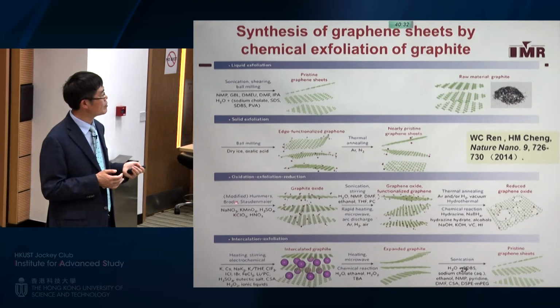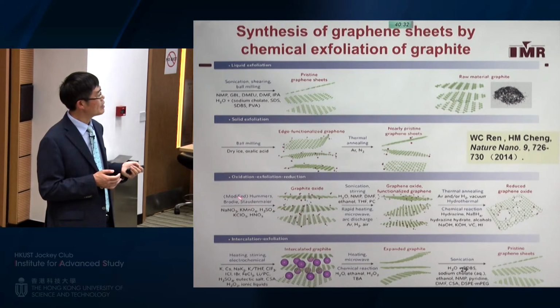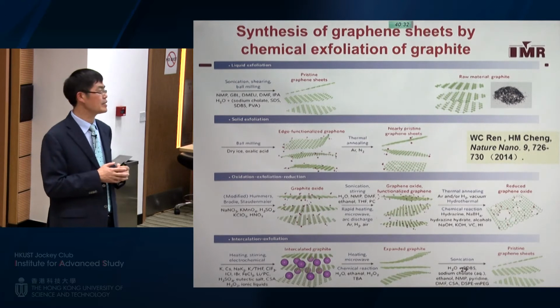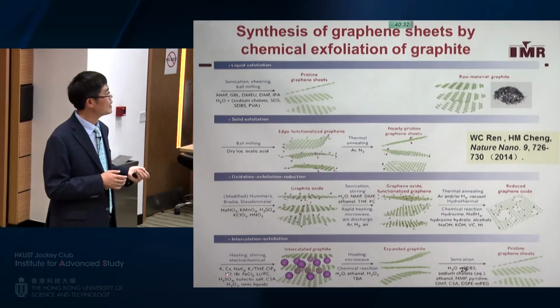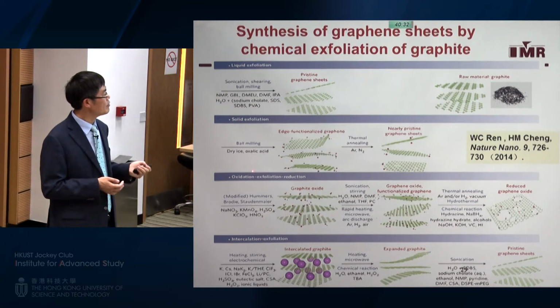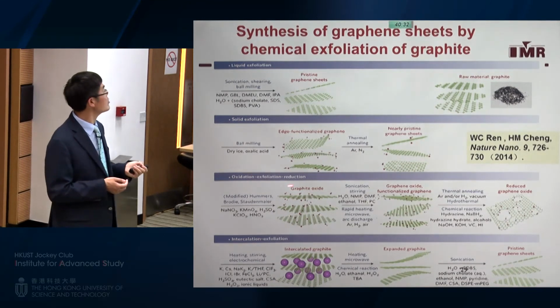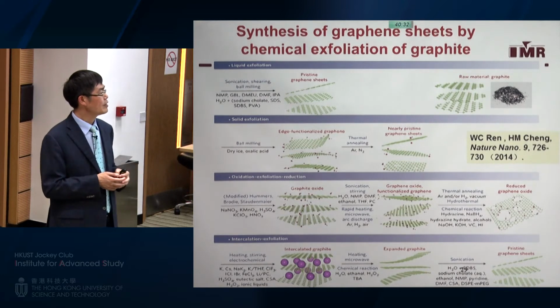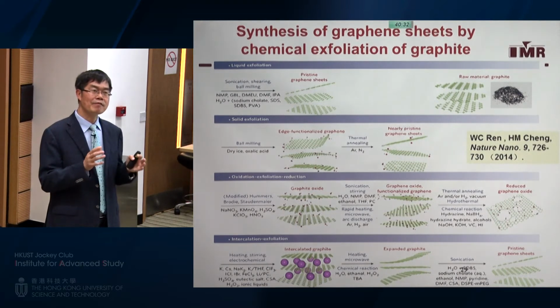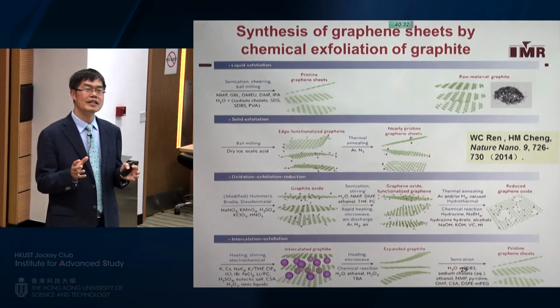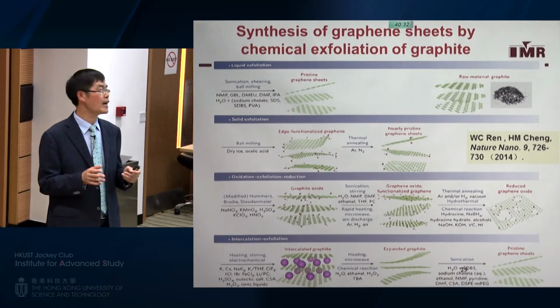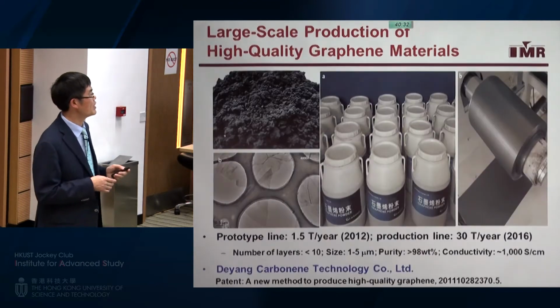But for those two methods, normally we need to add some chemicals like highly oxidizing agents or some salt. For the oxidation, exfoliation, reduction method, after oxidation, the material we obtain is graphene oxide. It's insulating. So we need to reduce it into reduced graphene oxide to be used in energy storage.